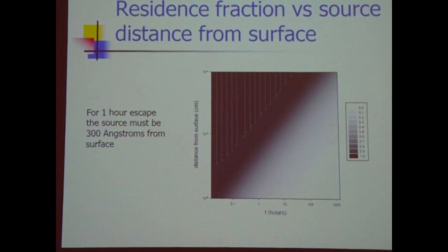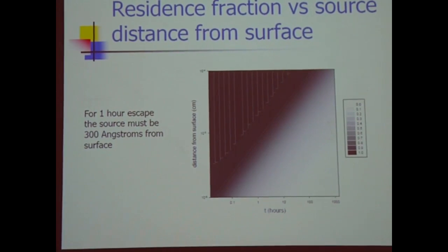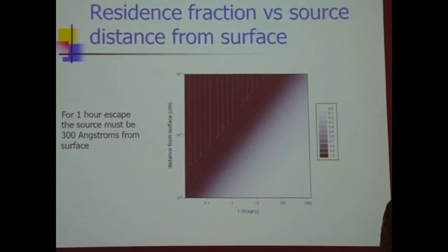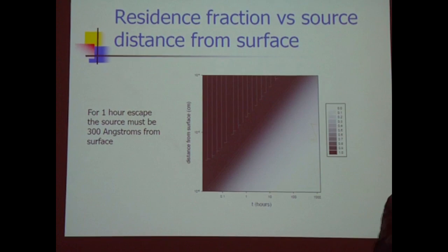Mind you, not in all excess heat experiments. For example, suppose you had an excess heat experiment where the amount of helium-4 production was not sufficiently high to plug up the vacancies. Well, in that case, you wouldn't see any temperature dependence. So there are experiments where temperature dependence is measured, but there's no temperature dependence. On the other hand, in the Fleischmann and Pons experiment, things are working really, really well. The notion is that under those conditions you're plugging up all the available vacancies with helium-4, and that would give you the temperature dependence associated with diffusing the helium-4 out.